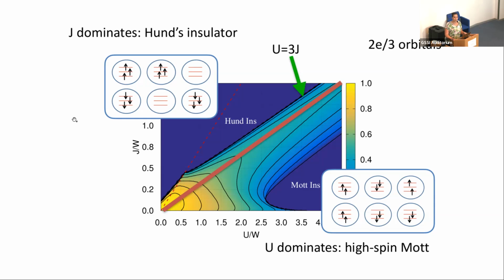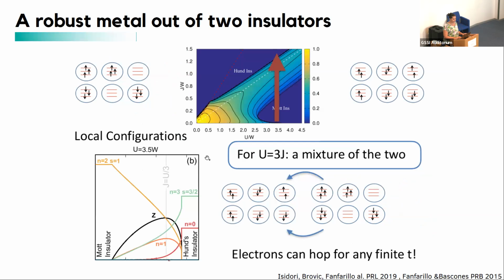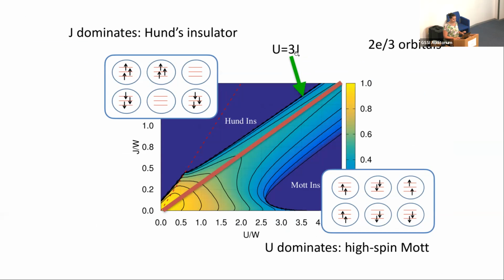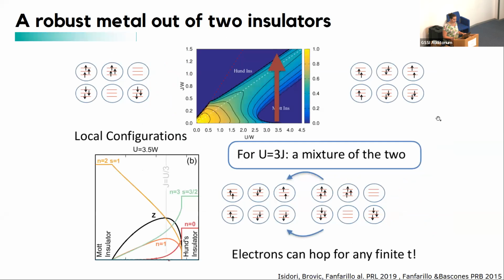Why am I discussing this in detail? Because you see that in between these 2 insulating phases, there is this extremely stable and nice metallic state. And this is along this J equal U over 3, as I was pointing out before. So what happens is that when you are in between these 2 insulating states, you have a mixture of these configurations. And as you can see now, you can move freely from one side to the other without costing any energy, because the density term is 0 at exactly J equal U over 3.